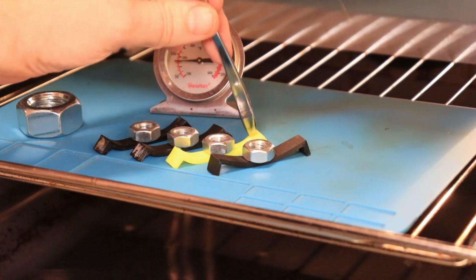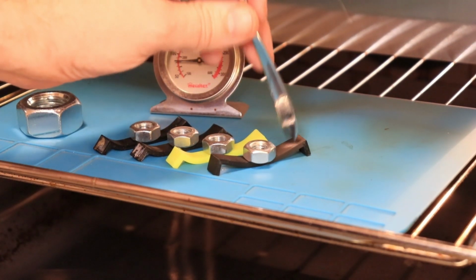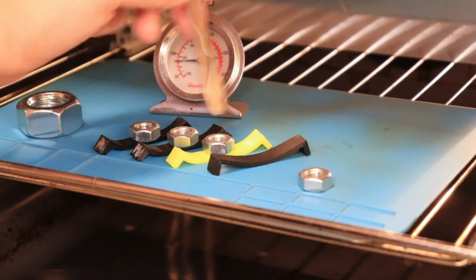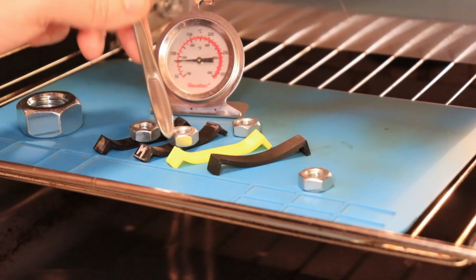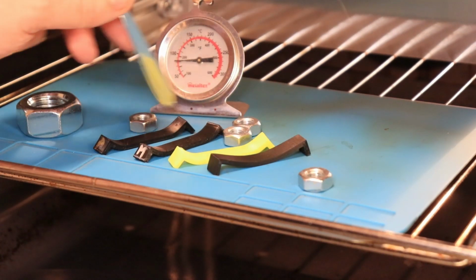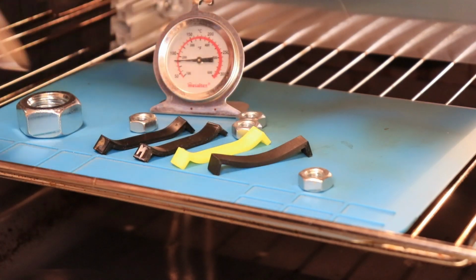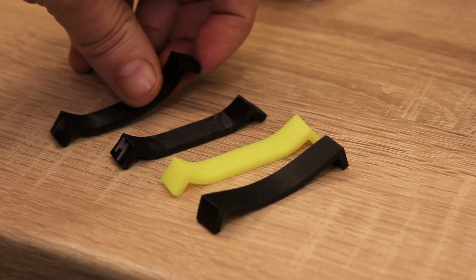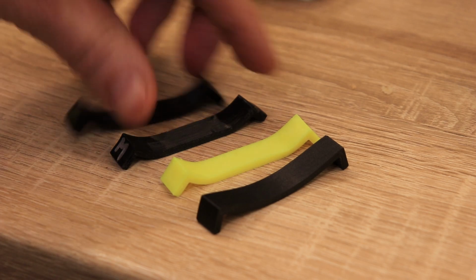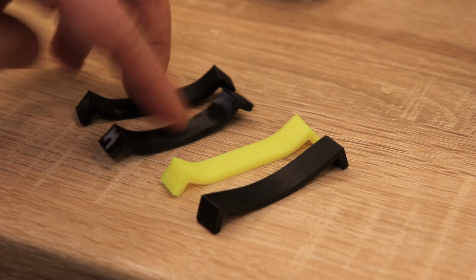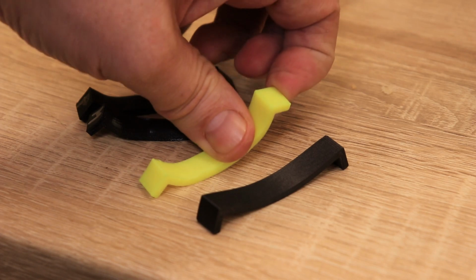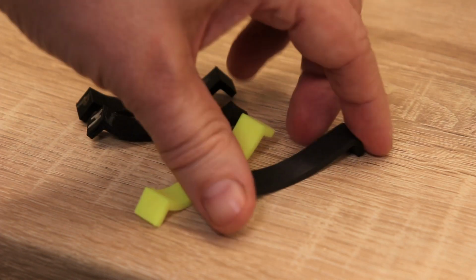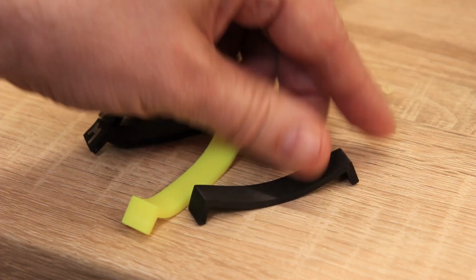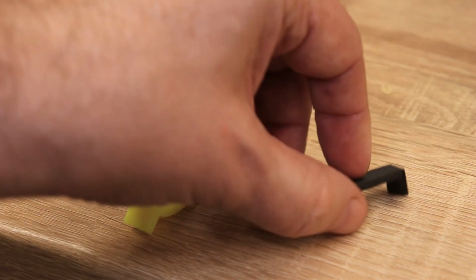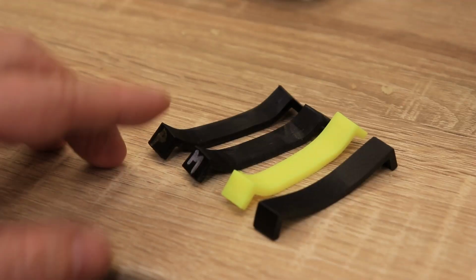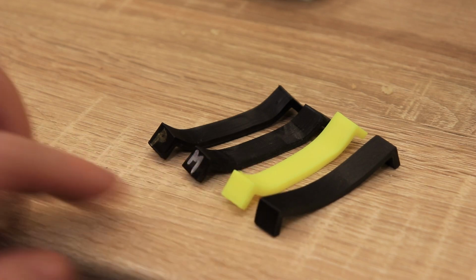For the filling, equal for these three, and this looks quite hard, and I can see less deformation on the carbon PLA. Well, they cooled down now a little bit, so I can touch them, and as you can see for the filling, these two are very equal, and also the PLA plus. And for the filling, I cannot deform this carbon PLA anymore. So in this test, the carbon PLA is the best.